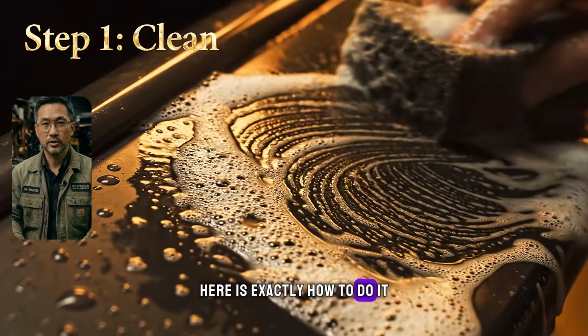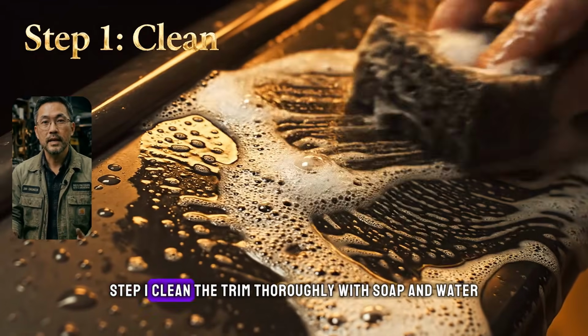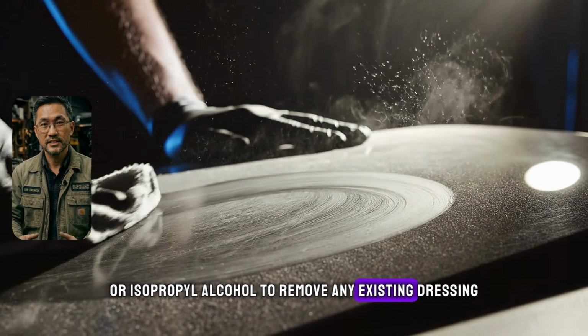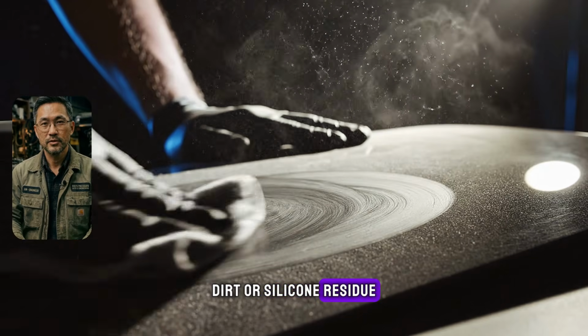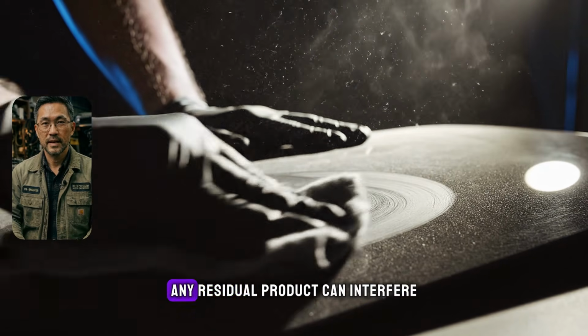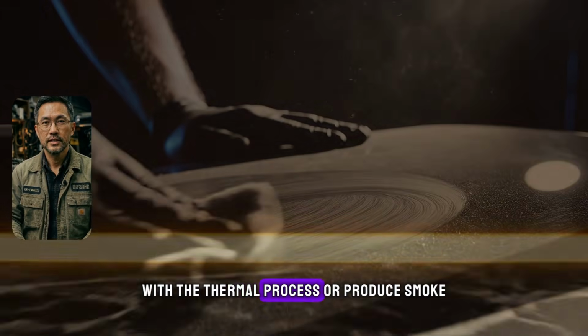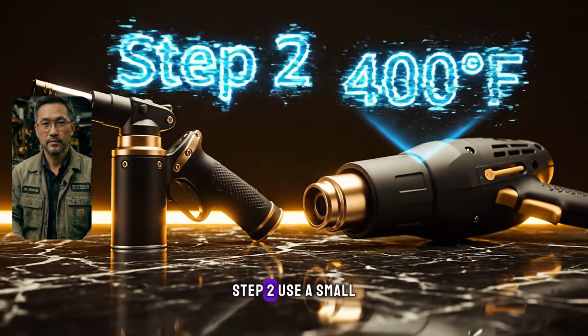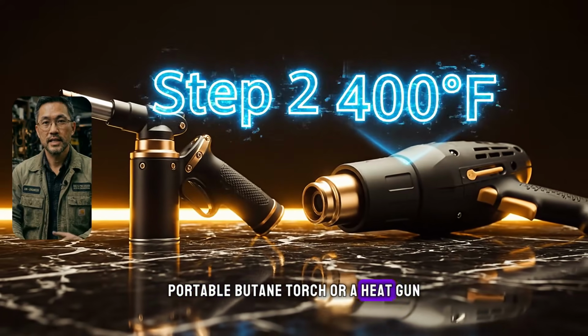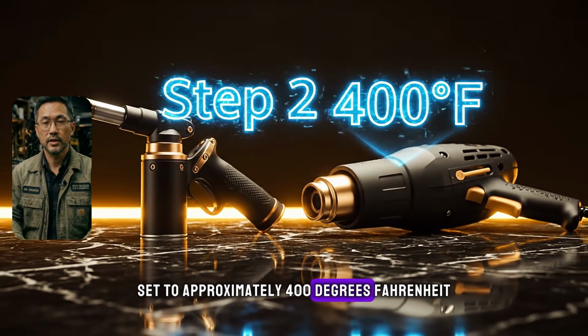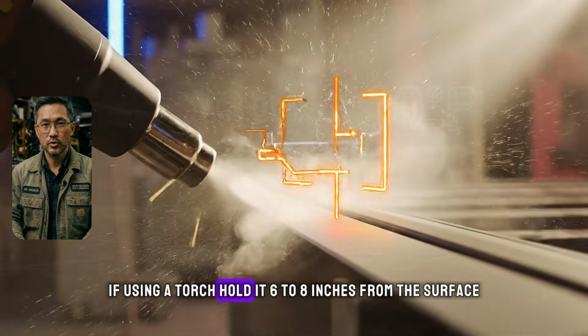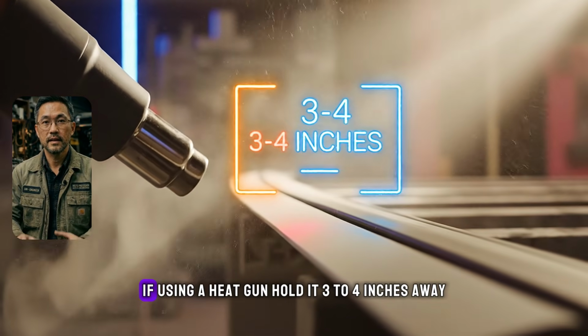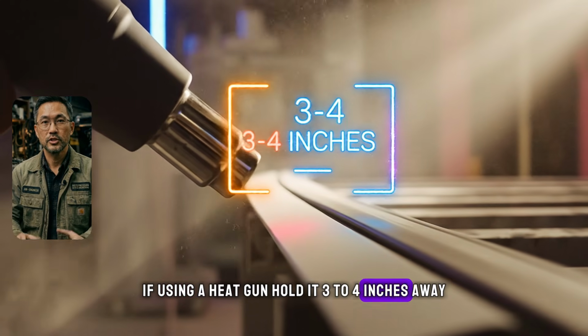Here is exactly how to do it. Step 1. Clean the trim thoroughly with soap and water or isopropyl alcohol to remove any existing dressing, dirt, or silicone residue. The surface must be clean and dry. Any residual product can interfere with the thermal process or produce smoke. Step 2. Use a small portable butane torch or a heat gun set to approximately 400 degrees Fahrenheit. If using a torch, hold it 6 to 8 inches from the surface. If using a heat gun, hold it 3 to 4 inches away.